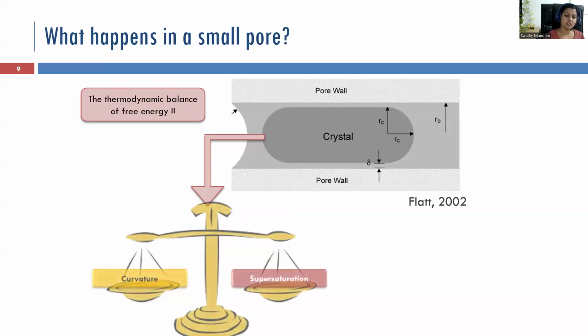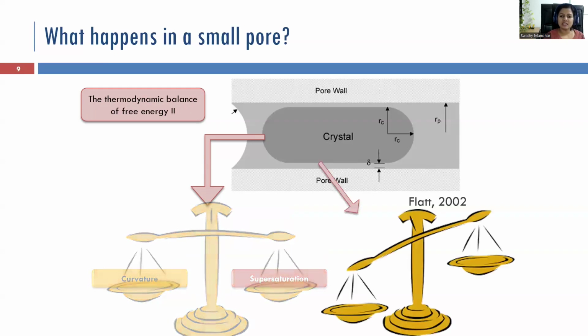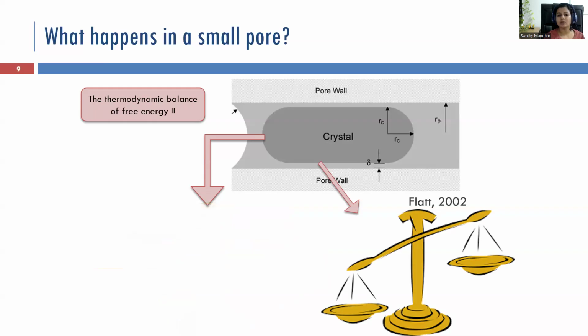The supersaturation of the solution is going to be very high in the water or solution to balance this high curvature. But if you look at this side, the curvature is almost half as that of the curvature at the hemispherical ends. So the curvature is very small. But the supersaturation of the same solution is already very high.